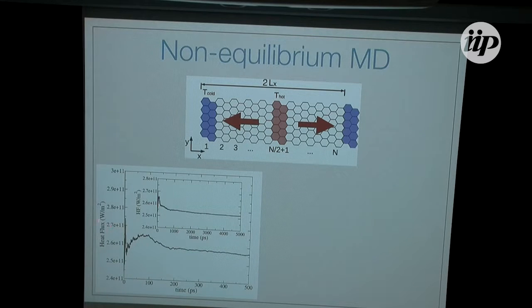If I look at the heat flux as a function of time, this is up to 500 picoseconds of simulation. There is some transient period here, and then it starts to reach some stationary state. Then if I look at a longer time scale, you clearly see that it does reach a stationary state, and that's the heat flux I'm going to use to calculate the thermal conductivity.